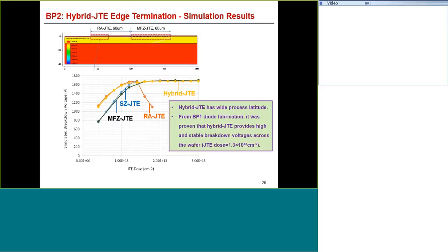If you use the MFZ JTE shown by the black line, it works very well at higher doses. And then if you look at the RA JTE shown by the red line, it works well at lower doses. So by marrying the two, you get what I could call the hybrid JTE, the orange line, and that is very broad in terms of process tolerance. So that is the one we are using in our designs.